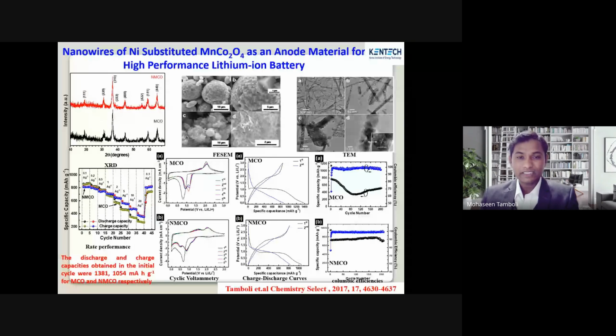The nickel manganese cobalt oxide electrode exhibited outstanding electrochemical performance. You can see there is 90% capacity retention and around 700 milliampere hour per gram even after 2000 cycles. Importantly, it has high discharge capacity with different current densities. Compared to the pure MnCo2O4, nickel substituted manganese cobalt oxide shows higher specific capacity.